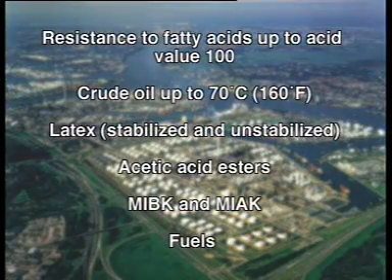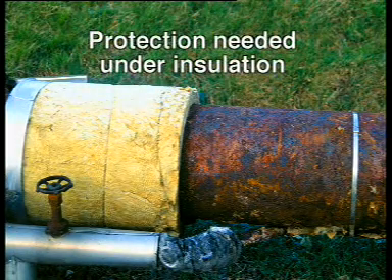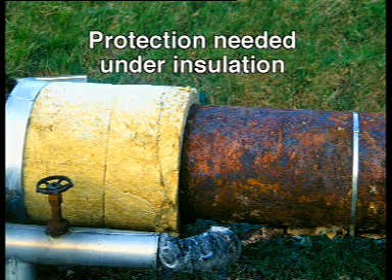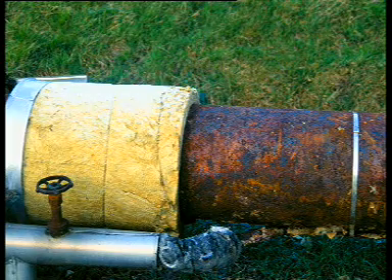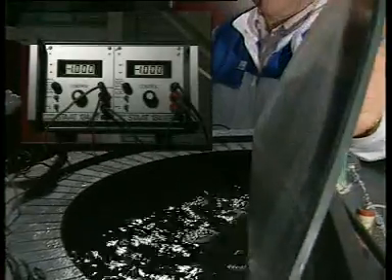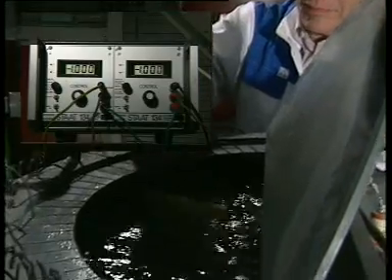Performance with aggressive crude oils and fatty acids is excellent, and it is also resistant to latexes, acetic acid esters, MIBK and MIAK, as well as all types of fuels. Novigard has excellent temperature resistance and can be used as a single coat system under insulation on pipes at operating temperatures up to 150 degrees centigrade (300 degrees Fahrenheit). Where cathodic protection is used, Sigma Novigard performs well without the need for a special primer.